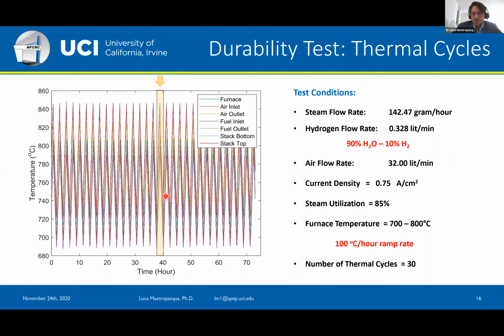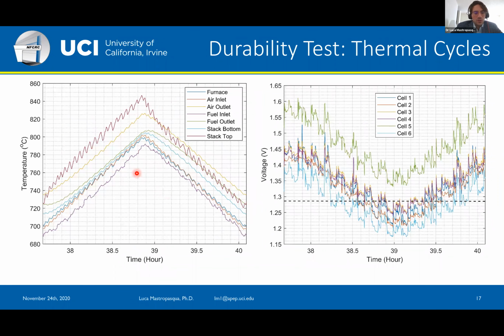the voltage performance. So I've focused on one of the cycles, and here, on the left-hand side, you see the variation of the temperatures inside the stack. The blue line is the furnace temperature that we control. All the other temperatures are measurements from thermocouples inside the stack. And you can see on the right-hand side the response of voltage performance of the 6 cells. So you can see the voltage dynamics is quite